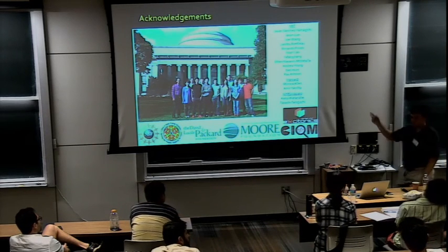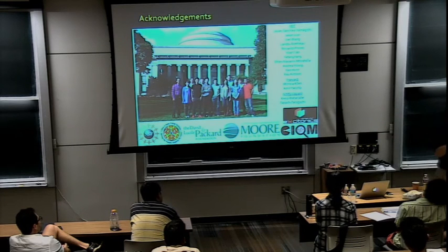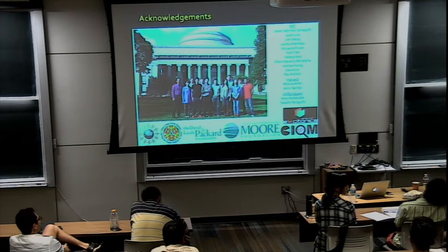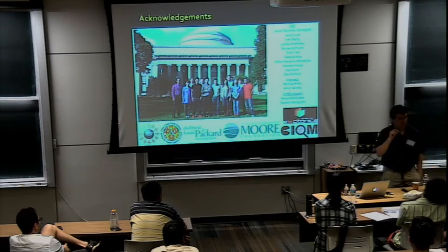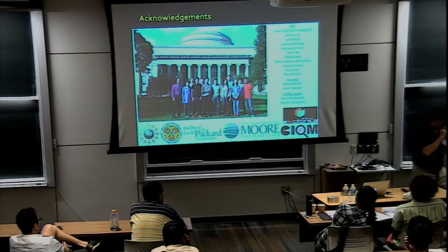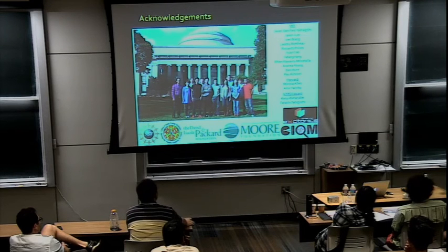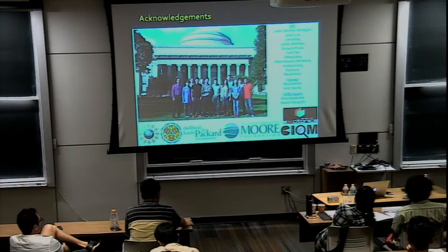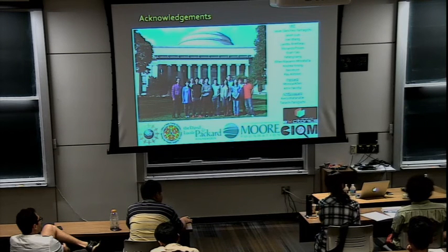So yeah, there have been plenty of studies of STM of graphene on HBN. You cannot measure the sign of the mass term with STM. What you can see, okay, in STM, most STMs that have looked into this work at several Kelvin in temperature. And in STM, your energy resolution in your bias is not great. So people have seen a flattening of the density of states, which they think has to do with the gap, but they haven't been able to measure a hard gap by STM spectroscopy.